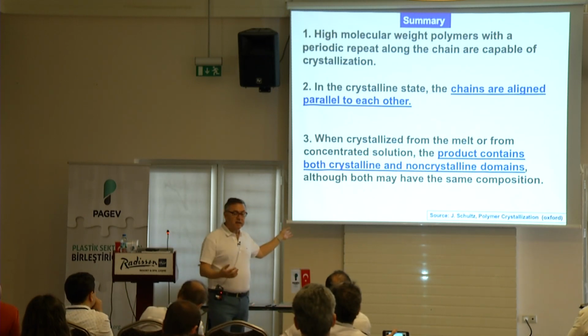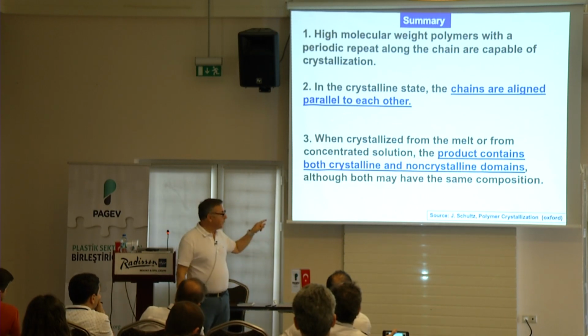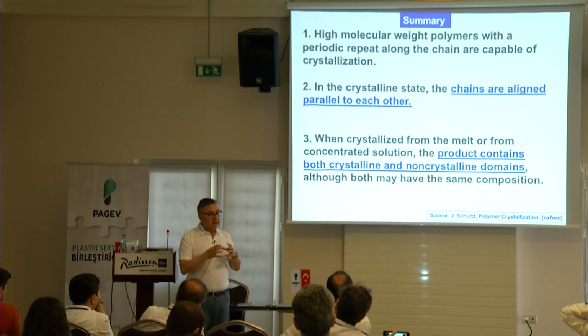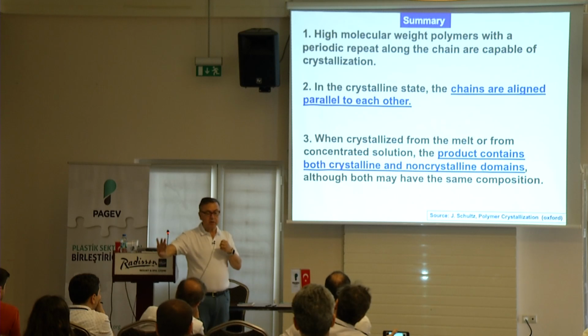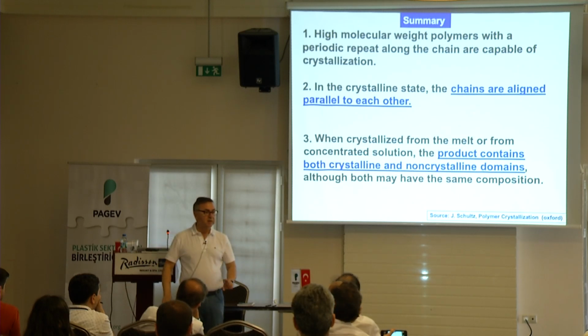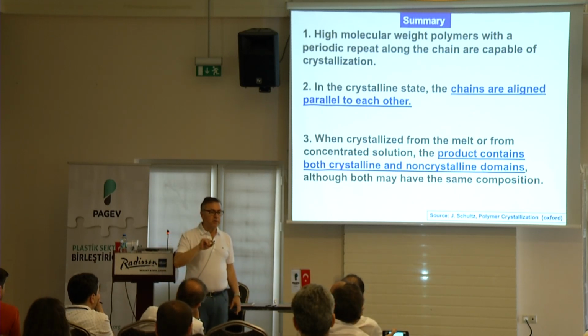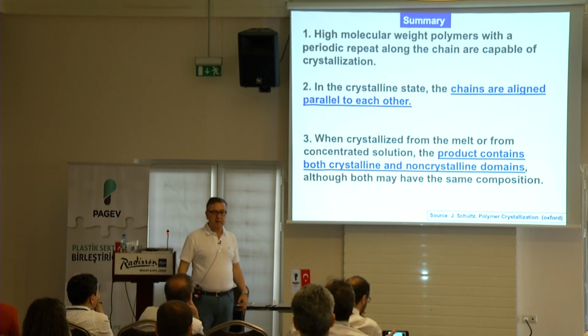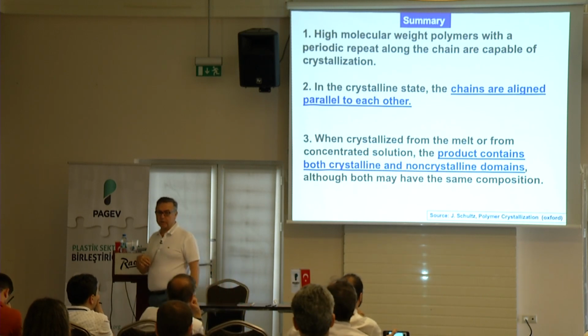There's always some other groups that are sort of a defect along the polymer chain. So what that translates into at the local level is that if they don't fit very well, they either act as a defect in the crystal or they get excluded from the crystal into zones between the crystals, where it will haunt you from a mechanical property perspective. It can deteriorate your material.